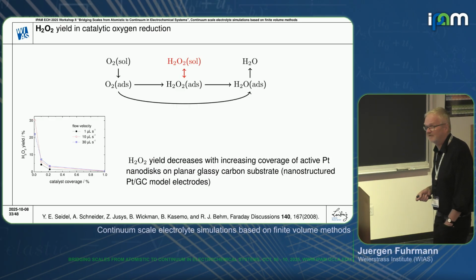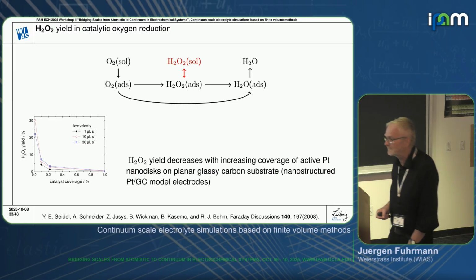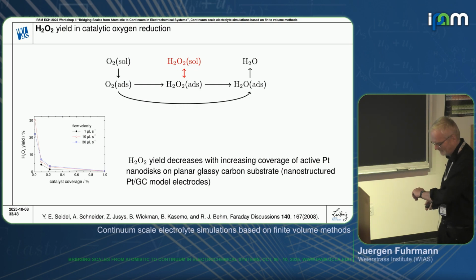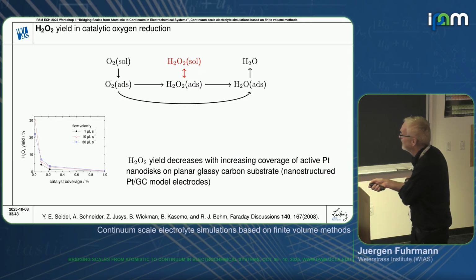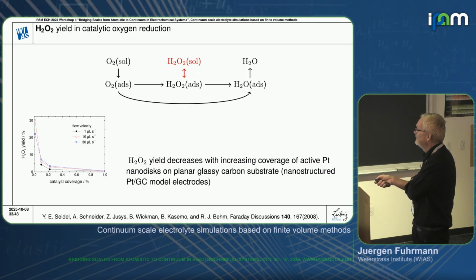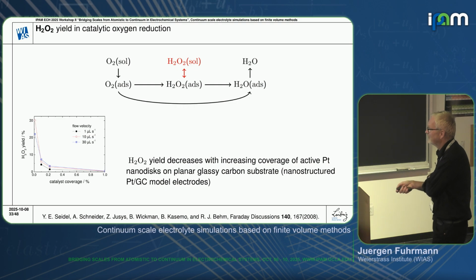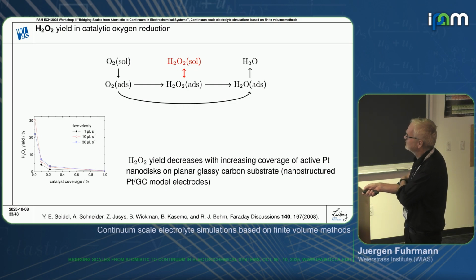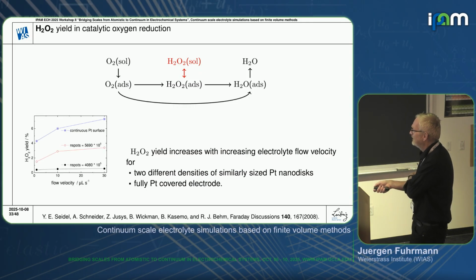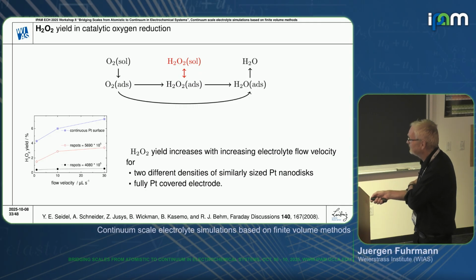Another experiment which has been made by the Behm group, which was mentioned also by Carsten Reuter in his talk, and that's why I'm also trying to talk about these things, is the multi-stage reactions, where we, for instance, have oxygen adsorbing and reacting on the surface to hydrogen peroxide and then to water and desorbing. And we can also get desorbing hydrogen peroxide as some intermediate product. The question is, how large is the share of the intermediate product in the overall reaction products? And the measurement says that with increasing catalyst coverage, the share of this intermediate product decreases. And also with increasing electrolyte velocity, the share of the intermediate product increases.